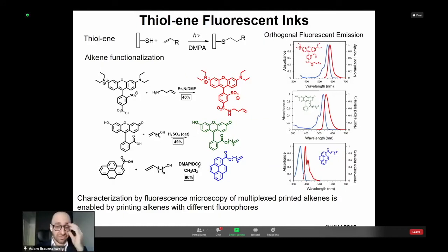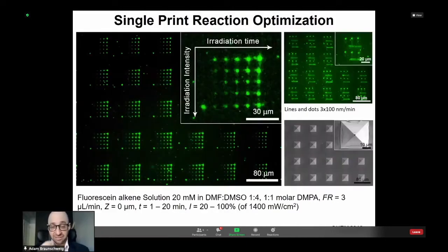So what we did for a proof of concept here was we just cooked up 3 different colored inks with an alkene in an effort to capitalize upon thiol-ene click photochemistry. So you take a thiol bound to a surface, you take an alkene, you shine light in the presence of a photoinitiator, and a new bond forms. And the 3 different colors are used so that we can leverage fluorescence microscopy to confirm that we have different materials on the surface.